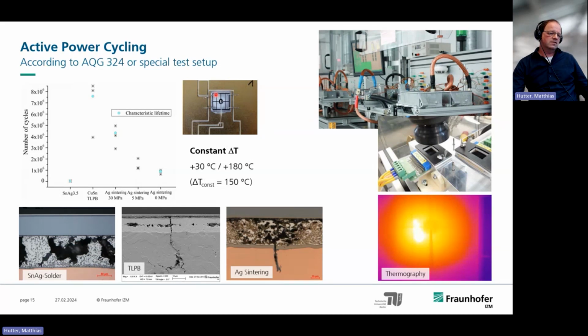So in this state, it is sufficient to use only very small wires, so that these wires don't fail during the test. This is very important. Otherwise, we could not really finalize the test. And using this very special setup, also with a constant delta T instead of constant current, we can then really compare different die attach technologies. And in this case, we did this comparison with tin silver solder, which failed after 40,000 cycles. Much better already was the silver sintering without using pressure. This was at around 400,000, so it's a factor of 10 already.